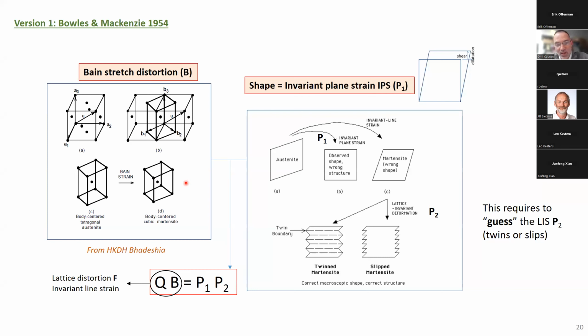The second problem is that I told you at the beginning that martensite has a lenticular shape, or a plate shape. It means that we imagine that martensite results from an invariant plane strain, which is encoded by a matrix P1. An invariant plane strain is exactly like a simple shear, except that we have a dilatation perpendicular to the plane to take into account the volume change between FCC and BCC.